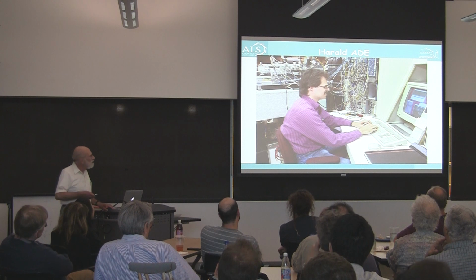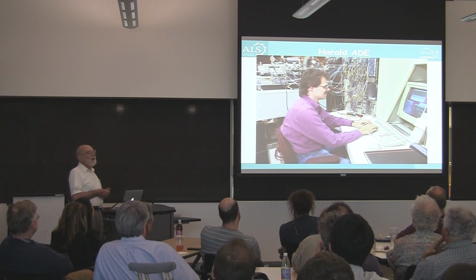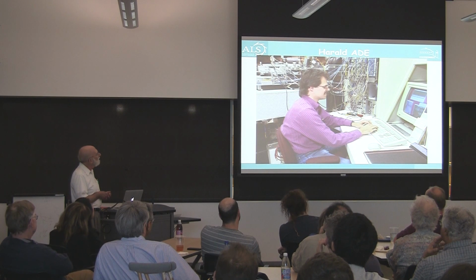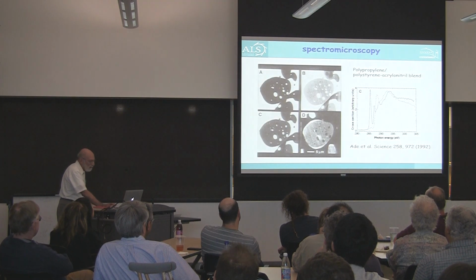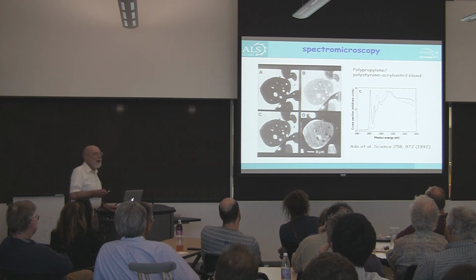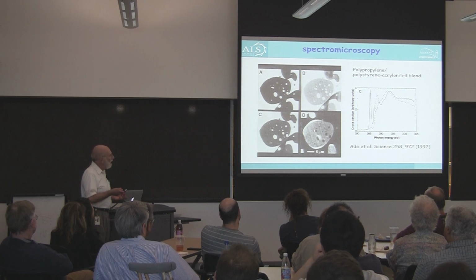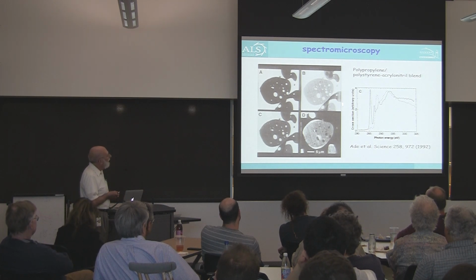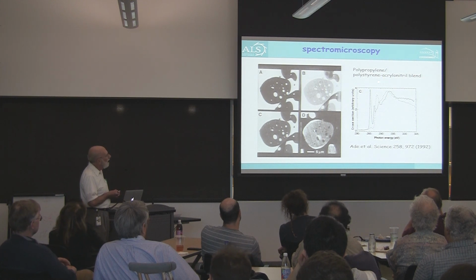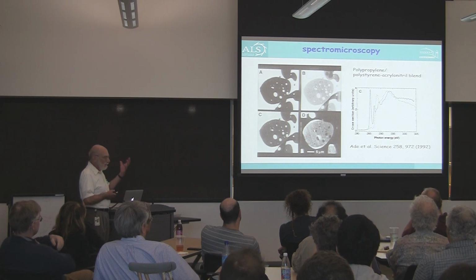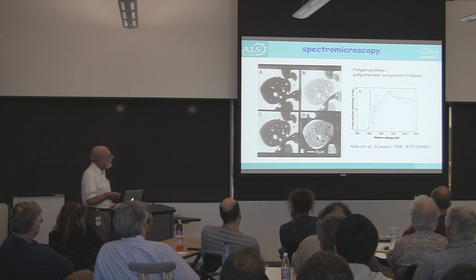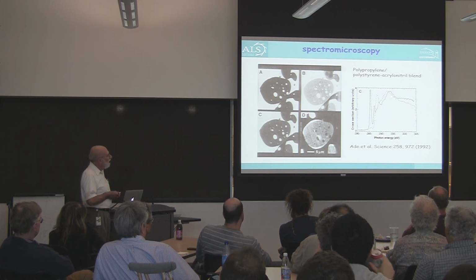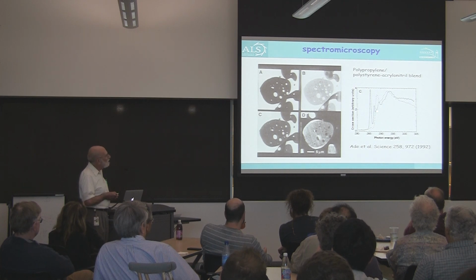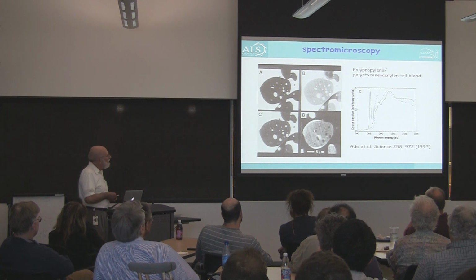Now, the person you see here is a fellow who many of you know. This is Harold Ade, and he was a graduate student and a postdoc with me at Brookhaven. And one of the things that he did was to get us involved in looking at the different components of polymers. Basically this was looking at a blend of polypropylene with a copolymer of polystyrene and acrylonitrile. When we looked at the model samples, it was very clear that the polystyrene acrylonitrile had a bunch of very pronounced resonant peaks near the carbon absorption edge, while polypropylene, which is shown dashed, shows a very different spectrum.